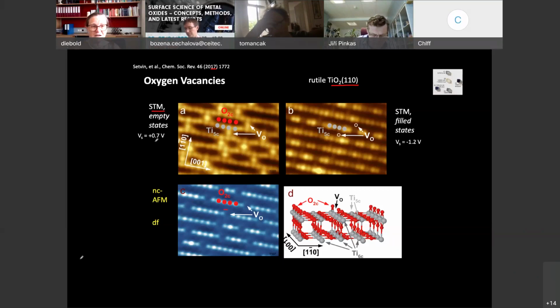And here we have the tip and the sample, and we measure the current between them, and the current can go 2 directions. It can either go from the tip to the sample, which is when the sample is positively charged, or it can go the opposite way, from the sample to the tip. This is when the sample is negatively charged.